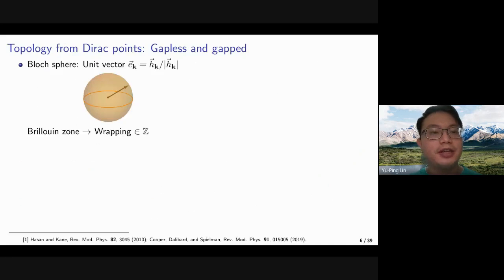So it turns out that there are some interesting topology from the Dirac points, which could arise from either the gapless or the gapped condition. So first, we could try to map the Hamiltonian onto a Bloch sphere, where we can define a unit vector as the direction of the pseudo field, and then it could go around the unit sphere. And the mapping of the Hamiltonian to the Bloch sphere could be thought of as wrapping the Brillouin zone onto the Bloch sphere, and the wrapping should correspond to a zero or finite integer.